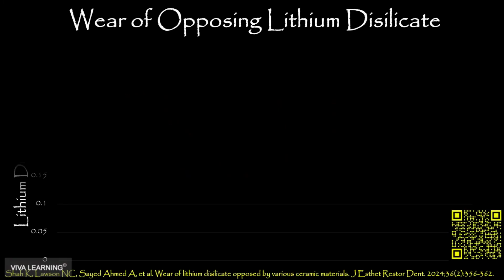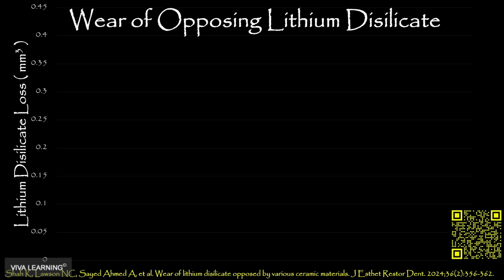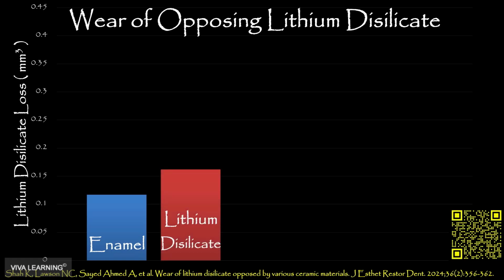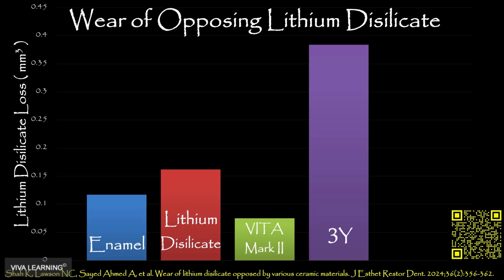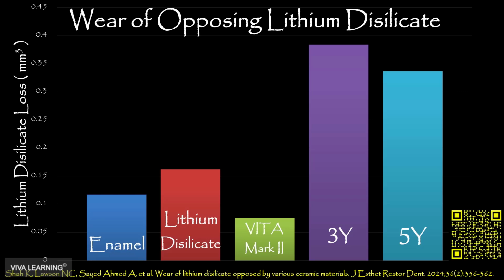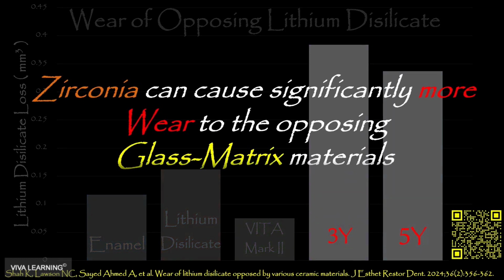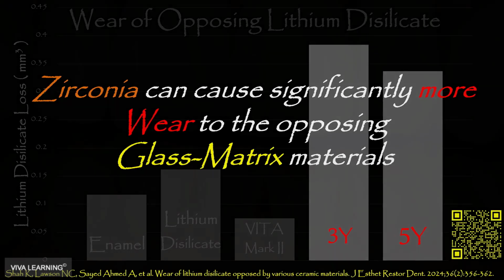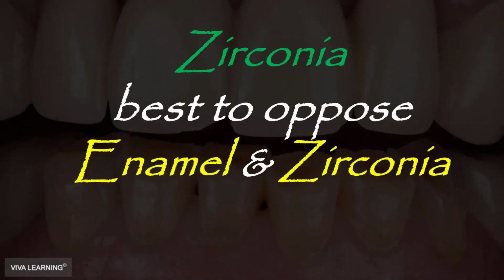However, when we checked how much wear of the opposing lithium disilicate we're going to get with different opposings, we could see that enamel and lithium disilicate could wear lithium disilicate to some extent. Mark II, which is feldspathic porcelain, did not cause much wear on lithium disilicate. But look how much wear we're going to get on lithium disilicate from 3Y and 5Y zirconia. This is significantly more, and that puts us in a position that we may need to conclude that zirconia can cause significantly more wear to the opposing glass matrix materials. So as a take-home message, we can say that zirconia would be best to oppose enamel or zirconia.